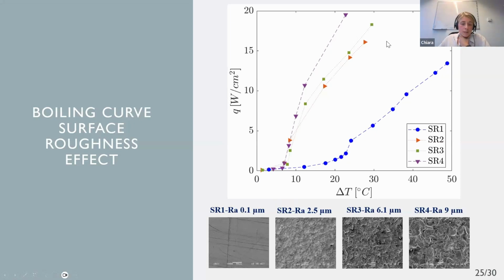So the limit of our operability increases to, I'm sorry that this is covering, but the maximum is around 18 watts per centimeter squared compared to 12 for the smooth surface. So we have an increase, already a huge increase, with just surface roughness modification.